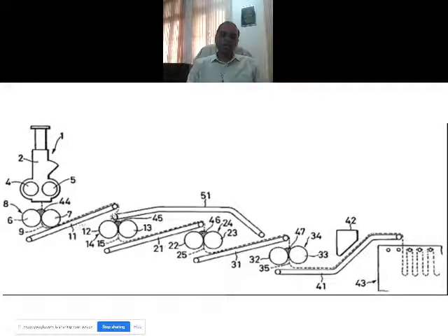This is a belt passing with rolls on it. So the ribbon that you cut, of sufficient width, will pass over this and will be transported to another two-roll mill for further refining. This is for making a sheet and this is for refining. This is also for improving dispersion. Each of these stages is for better dispersion. The idea is, instead of changing the nip gap here, you can change the friction ratio to different values, and finally there is cooling.